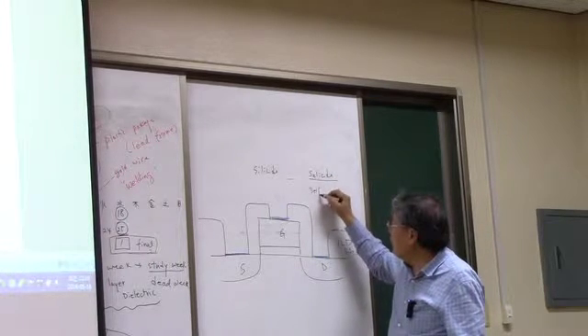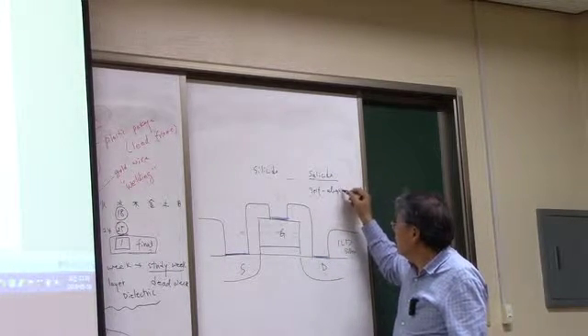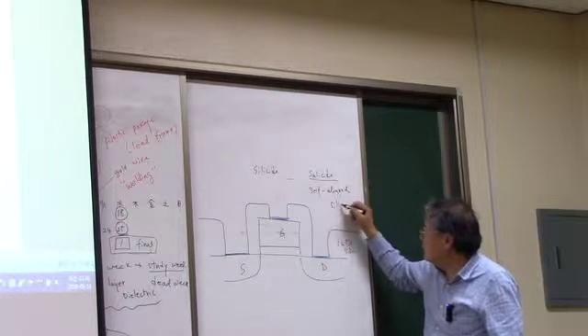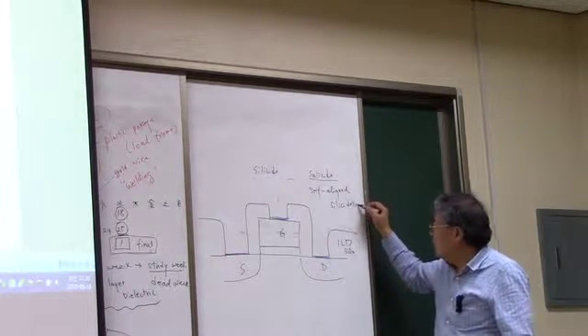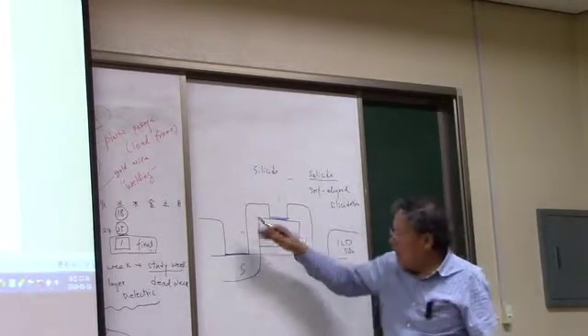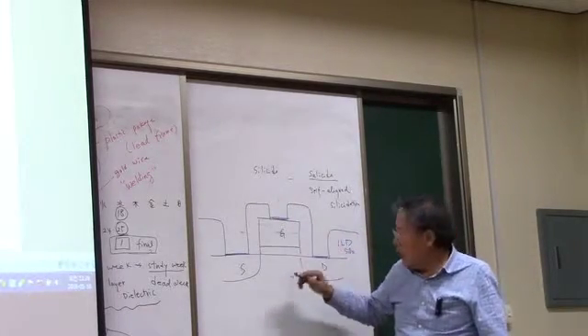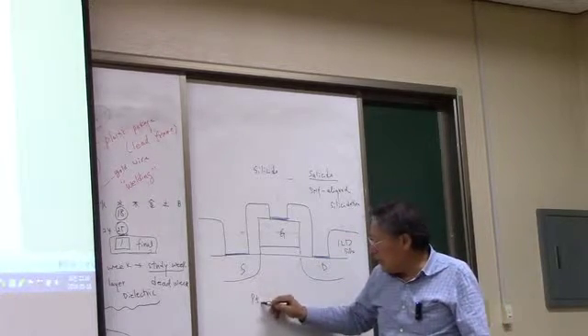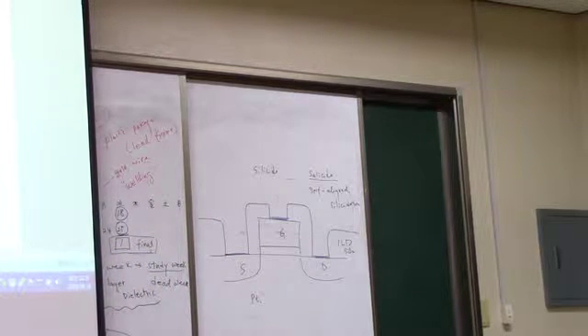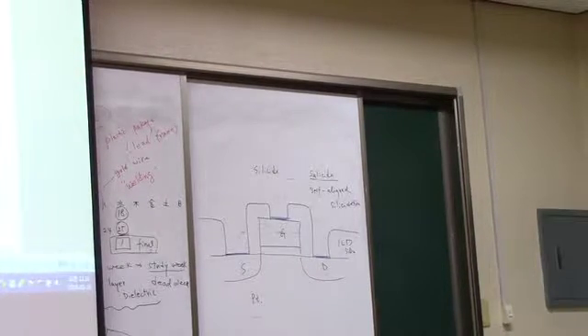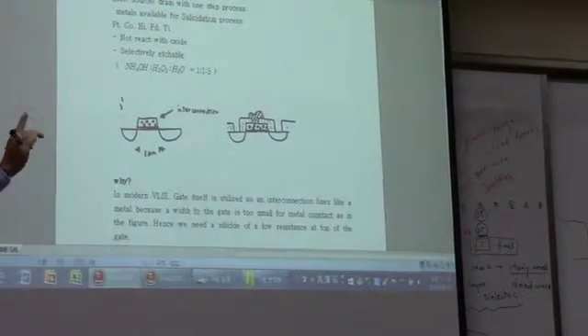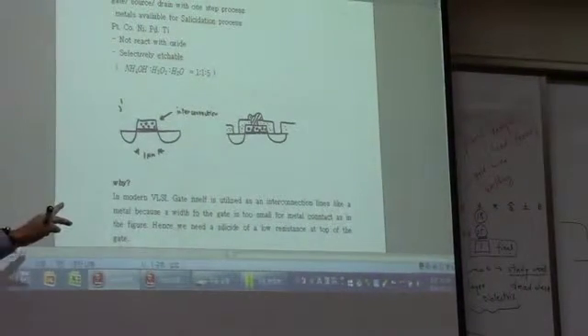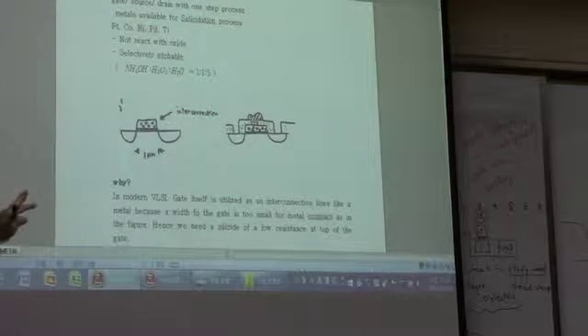But in this silicide process, this is a self-aligned silicidation. You do not do the lithography after the metal deposition. Some of the materials, platinum, have been listed here. This silicide is not available for other elements but platinum, cobalt, nickel, palladium, titanium. Only these 5 elements can do the silicidation process.